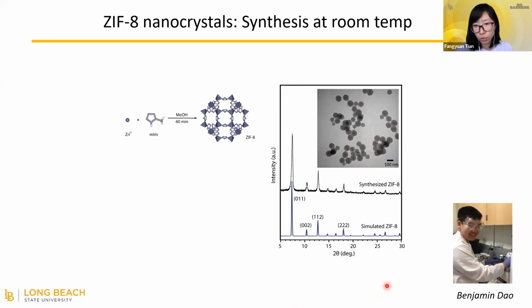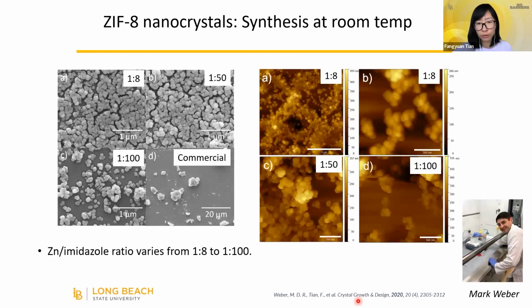And this work has been done by Benjamin Dow. He is an undergrad student in my lab. Later on, we found that if we change the ratio between zinc and 2-methylimidazole, we can adjust the particle size and change the morphology. With a higher ratio, or a higher amount of 2-methylimidazole linkers, all of those particles just aggregate together. So we could tune the size and the morphology.